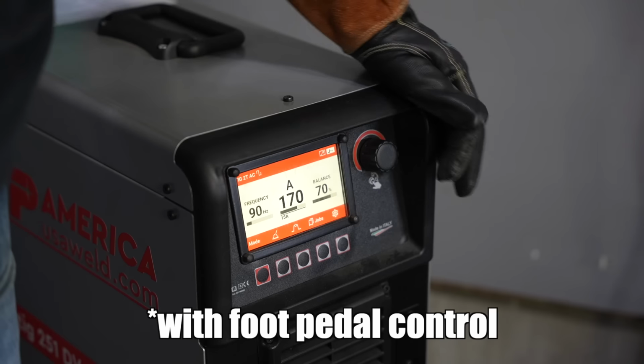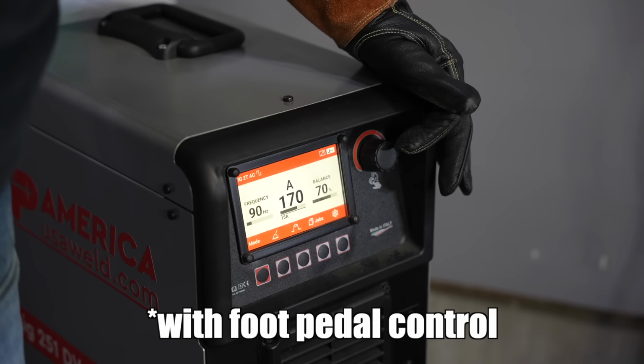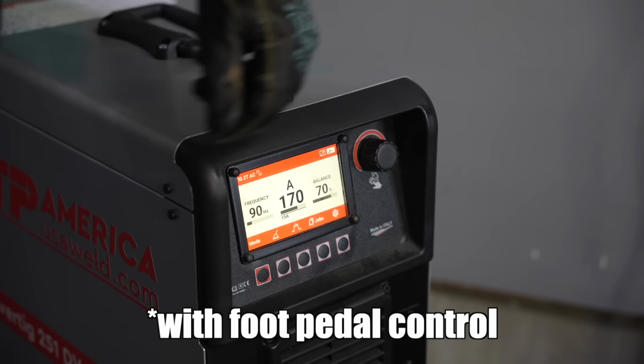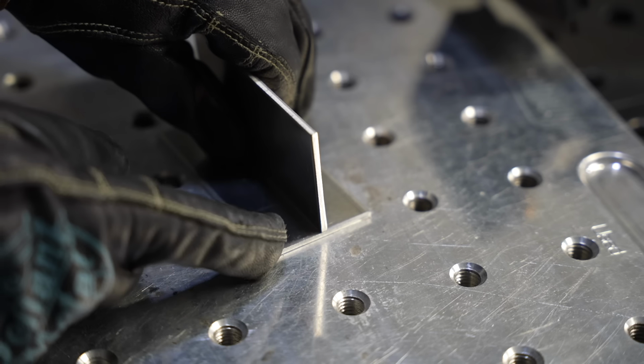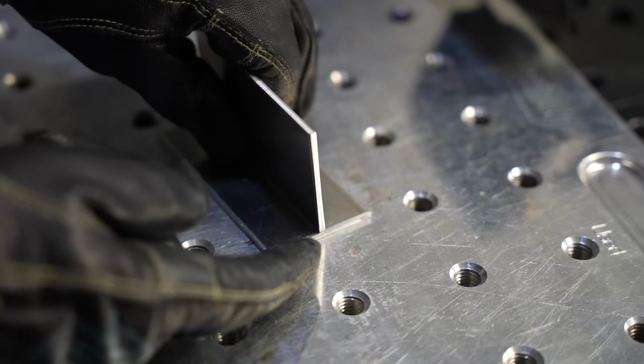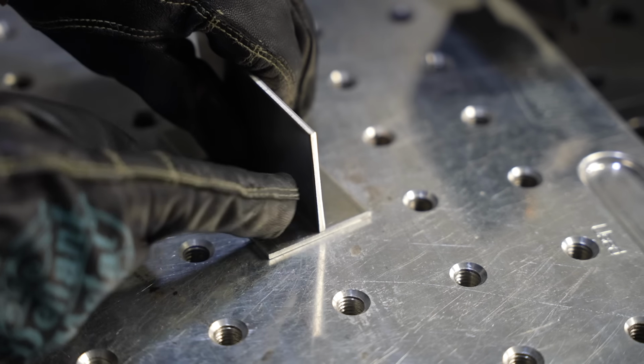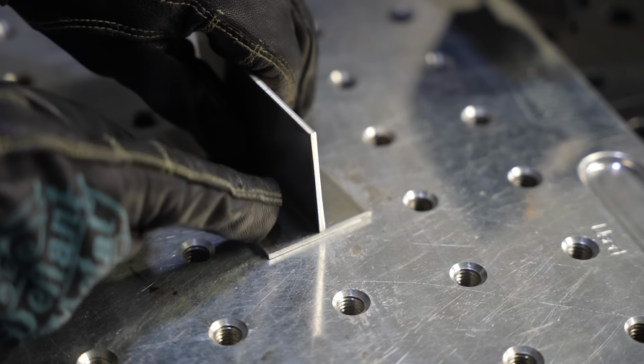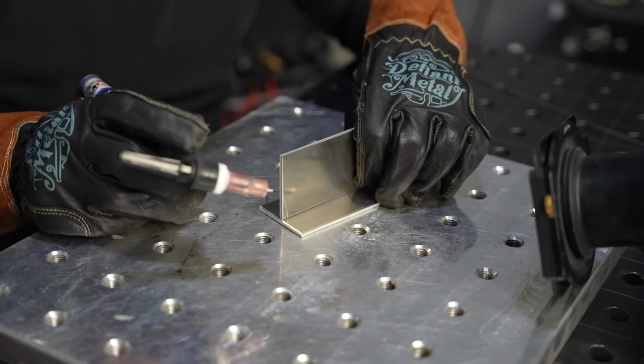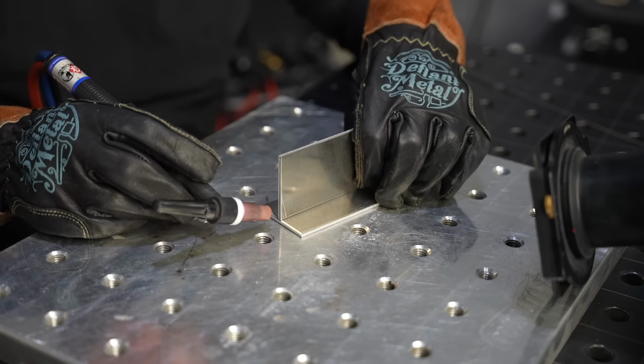I'm gonna turn it clear up to 170 amps here for this 1/8 inch thick material, and then control it with the foot pedal. Now the reason I need more amperage is I'm heating up a lot more material in here, and it's being carried away in 3 different directions, and aluminum can really soak up the heat pretty fast. Higher amperage also makes it a lot easier to tack without any filler metal.